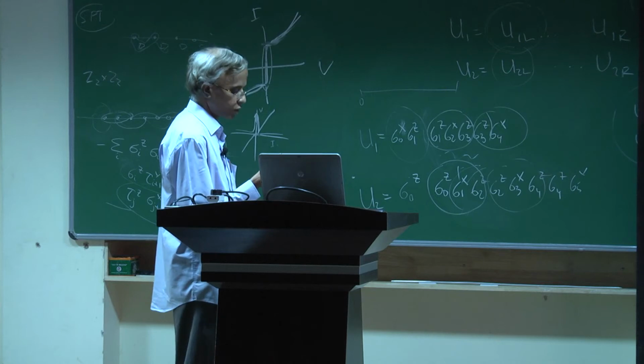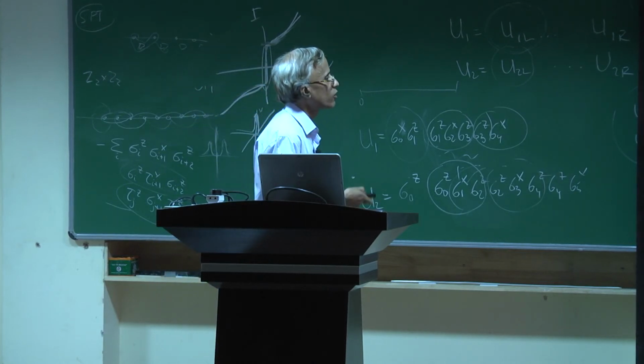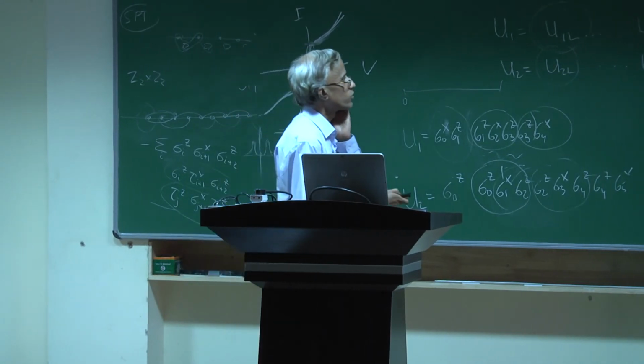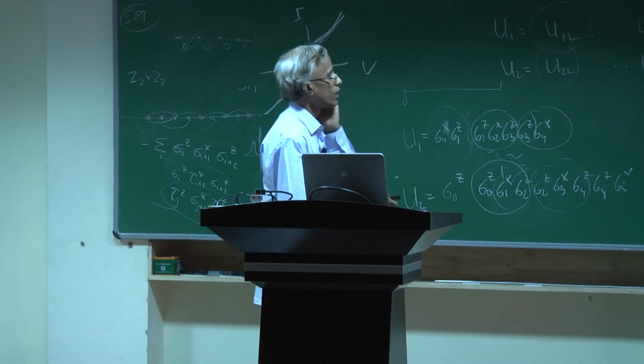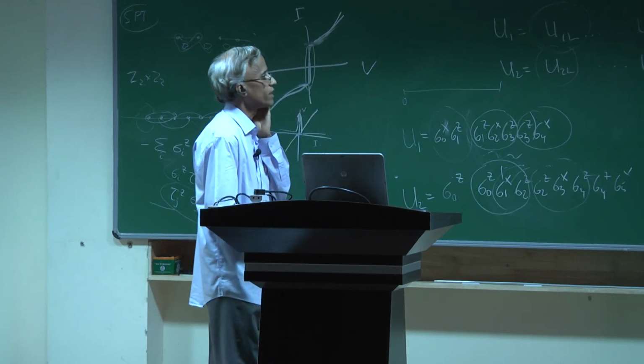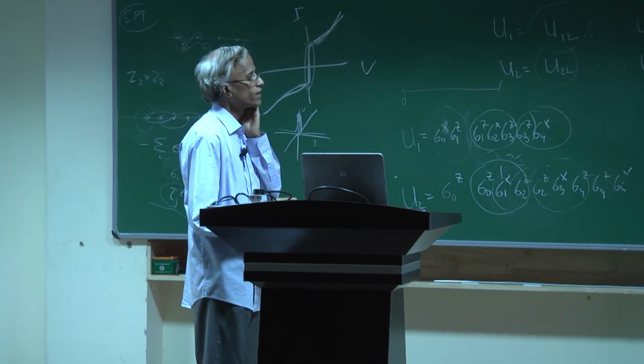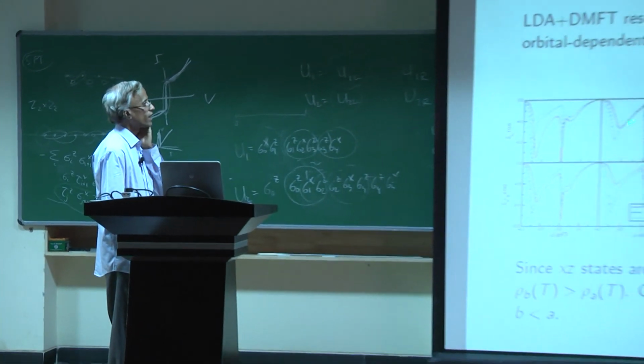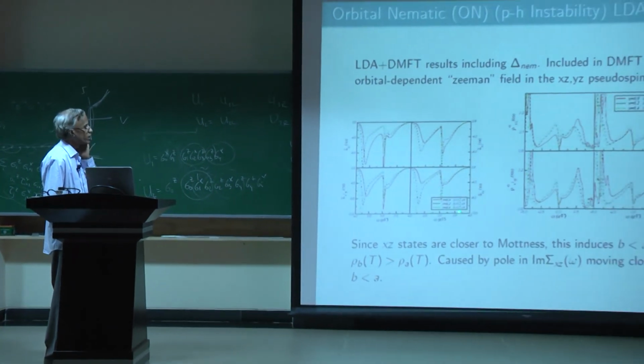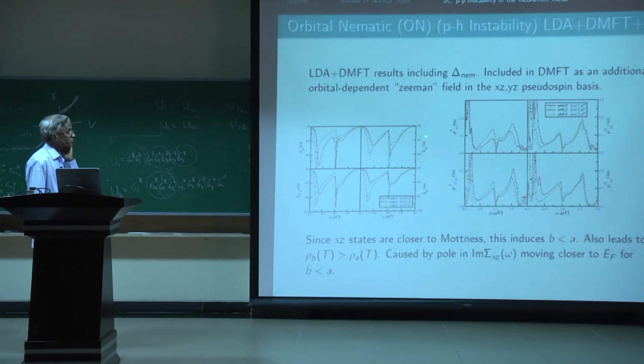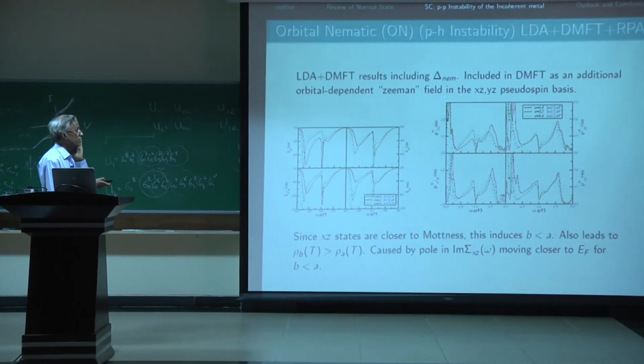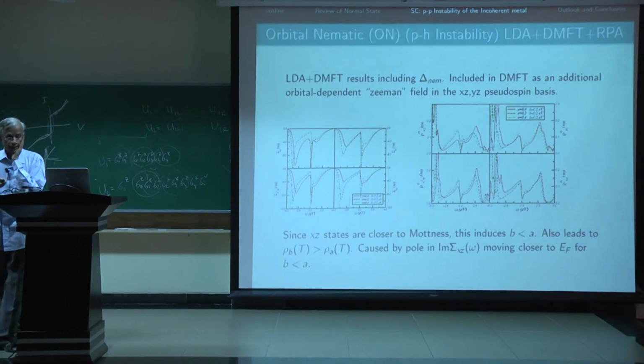I'm almost done. So from this observation, you can calculate, and this is what we've done more recently, but I'm not going to show that. Please feel welcome if you want more information. What one sees is that the resistivity along this direction is insulator-like, and along the B direction is metal-like, but bad metal-like. And this bad metallicity actually increases with doping, exactly as seen in the resistivity data that I showed you.